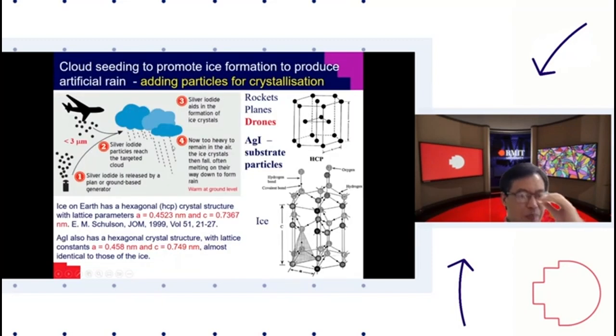And then the production of artificial rain is very popular, and it's based on adding particles into the moisture-heavy clouds. We call that cloud seeding, and the particles introduced are normally less than 3 micrometers. These particles are silver iodide. After seeding the cloud with the particles, there will be easy formation of small ice crystals. These small ice crystals will keep growing until they become too heavy for the cloud, and then gravity will draw them towards the surface of the earth.